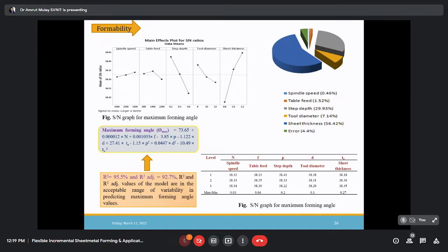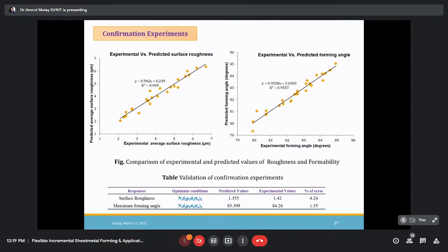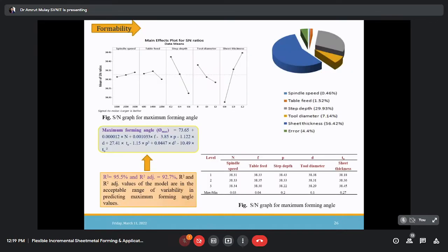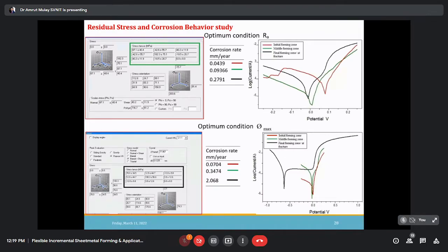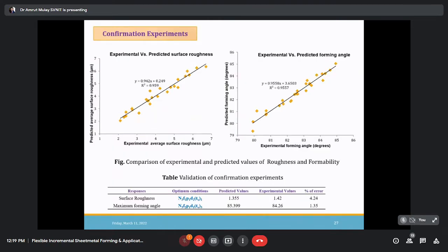formability. So now we can say that we have confirmed the experiment, and we have confirmation. It means that whatever conclusion we made, that is up to the mark for the given CNC machine, for a given material, right? So now we have seen the corrosion rate we studied. The optimal value that came, you see that surface roughness and the maximum forming angle, we got this optimal condition. This optimal condition is N3, F1, P1. What is N3, F1, P1? It means the speed at level 3, feed at level 1, step depth at level 1, D indicates tool diameter at level 2, and sheet thickness at level 1. So these are the optimal conditions for surface roughness and forming angle.